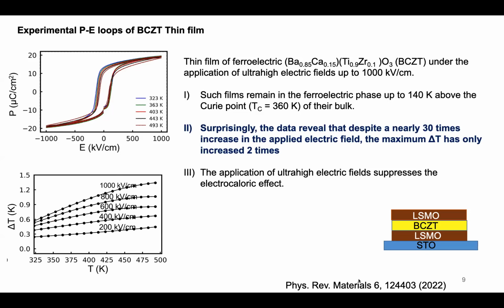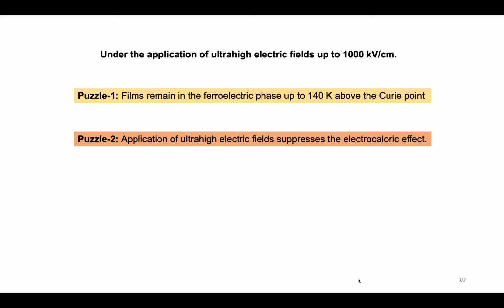And the second thing, another discouraging part, is that they got the change in temperature of only 1.2 Kelvin, which is kind of discouraging. In the bulk, they were able to apply around 40 kV per centimeter, and here it's up to 1,000 kV per centimeter. So of course, one would expect at least not a 30 times increase in the change in temperature, but at least going up to 20 Kelvin or 15 Kelvin. But the maximum change in temperature here is 1.2 Kelvin. So here the suppression has happened in the electrocaloric effect. So the two puzzles they offered us are that, first, the film remains in the ferroelectric phase 140 Kelvin above the known Curie point, and the application of this high field has suppressed the caloric effect.